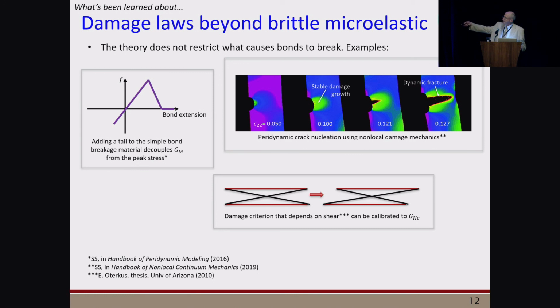But by putting a tail on that material model, you can alter the area under this triangle, allowing you to independently determine both the maximum stress that the material can sustain as well as the critical energy release rate. You can also implement bond failure criteria that respond to rotation angle between bonds, in other words, shear, allowing you to independently specify G2C as well as G1C. And you can do fancier things like develop a nonlinear or non-local damage mechanics approach to failure of bonds.